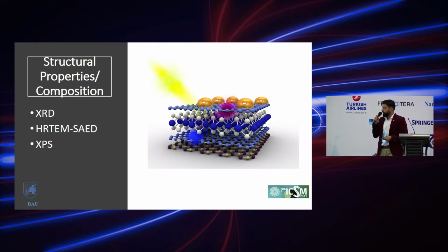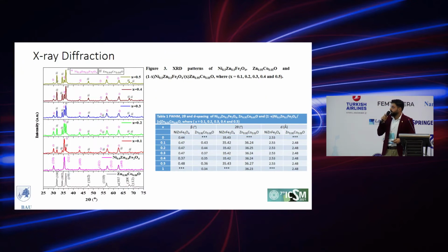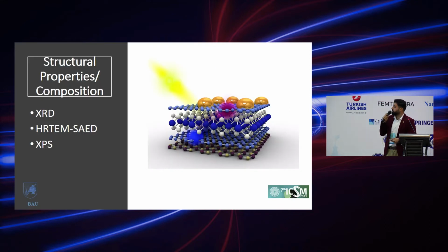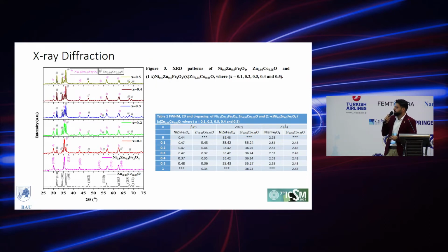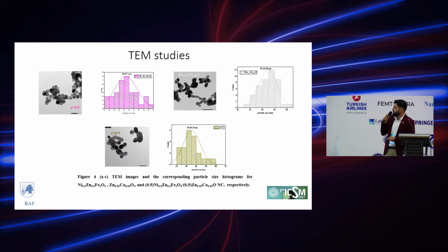Concerning the structural properties and composition, the X-ray powder diffraction spectra have proven the existence of both phases, zinc cobalt oxide and nickel-zinc ferrite, without any traces of other impurities. The two theta values and the lattice spacing have shown no variation with the nanocomposite addition, which confirmed the stability of the phase and the absence of chemical interaction or substitution between the ionic species forming the nanocomposites.